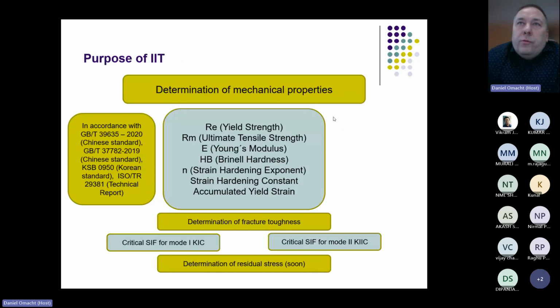What is the purpose of IIT, of instrument indentation test? We use it for determination of mechanical properties, as a yield stress, ultimate tensile strength, Young's modulus, Brinell hardness, strain hardening exponent, strain hardening constant, and accumulated yield strain, or for determination of fracture toughness. Here we can determine K1C, or determination of residual stress.